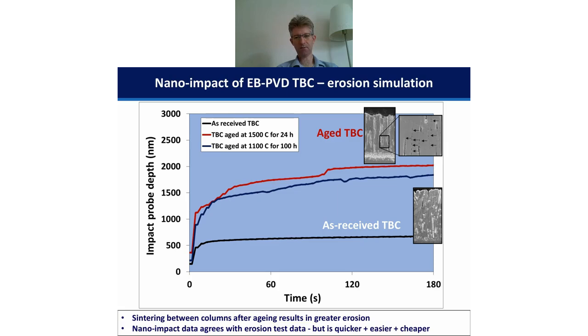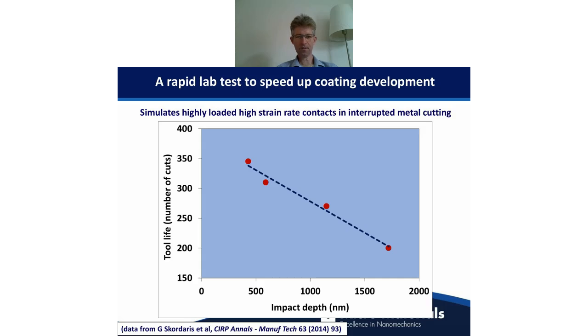And if we look at the microstructure, we can actually see what's happening is that when the material has been thermally aged, this columnar structure, which provides some strain tolerance, is starting to sinter together. And that sintering across the columns is decreasing the strain tolerance such that when it's impacted or eroded, then essentially material from many columns can be removed. But when it's not thermally aged, essentially that can remain within one column. So there's big disadvantages in this case for thermally aging. But this is just here to show the advantages of the nanotest and how to optimize this sort of performance.